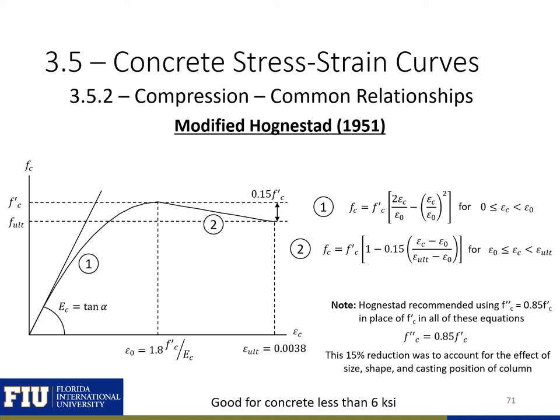Note that Hognestad originally proposed that a value of f''c equal to 0.85 f'c be used in place of f'c in all of these equations. His research was aimed at modeling the behavior of reinforced concrete columns, and this 15% reduction took into account the effect of size and shape of the column, as well as the casting position. For design, to account for the difference between the in-place strength and the cylinder strength, you can use 0.9 times f'c in these equations.